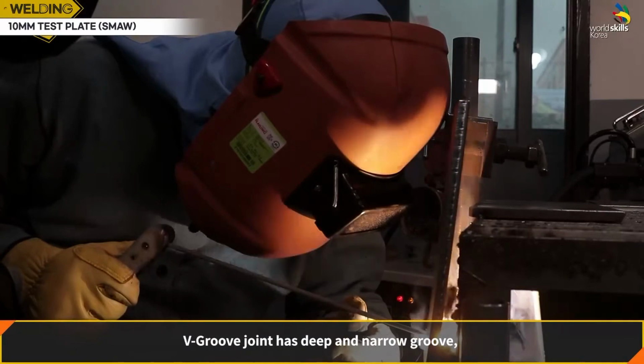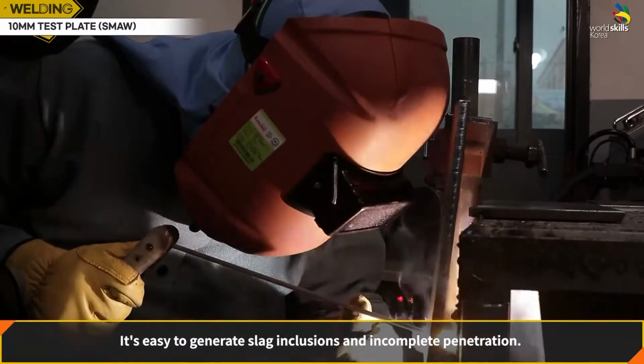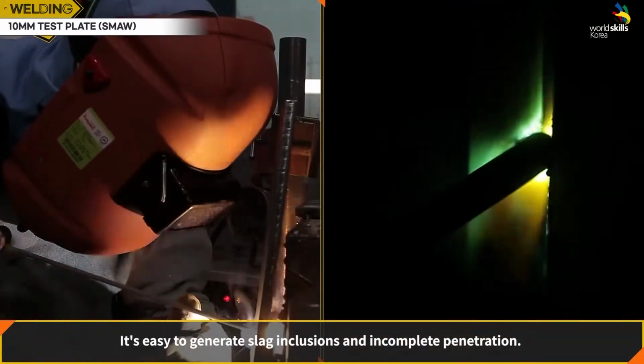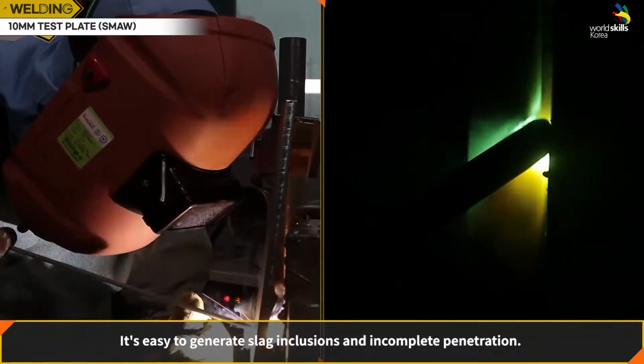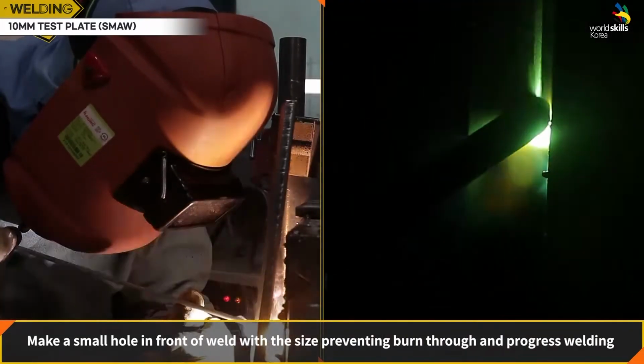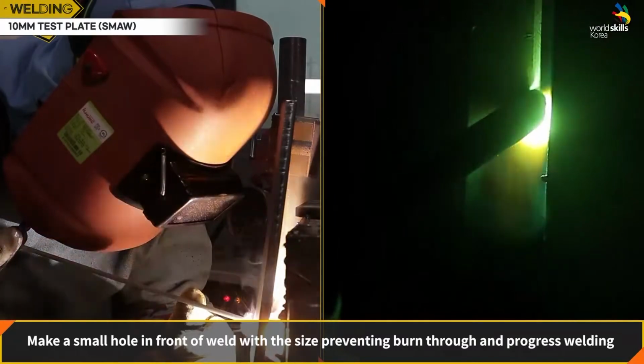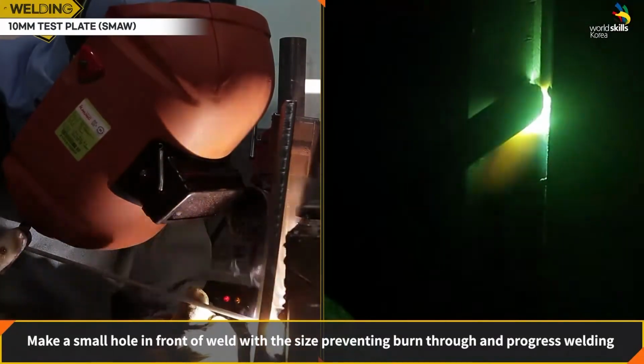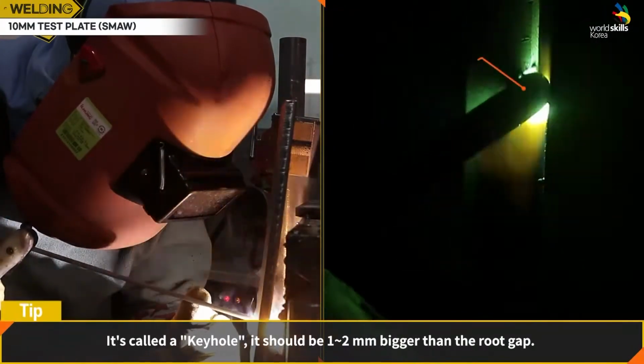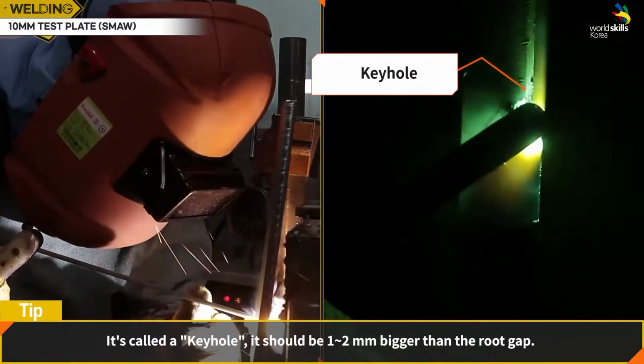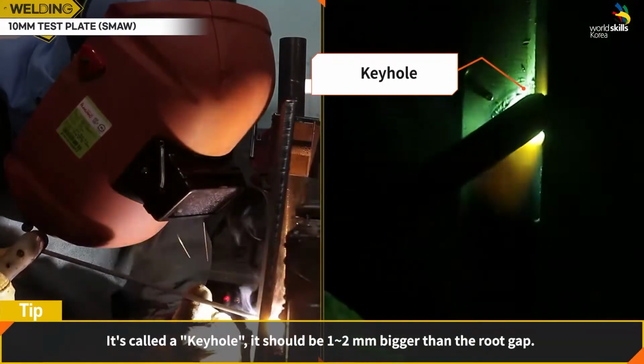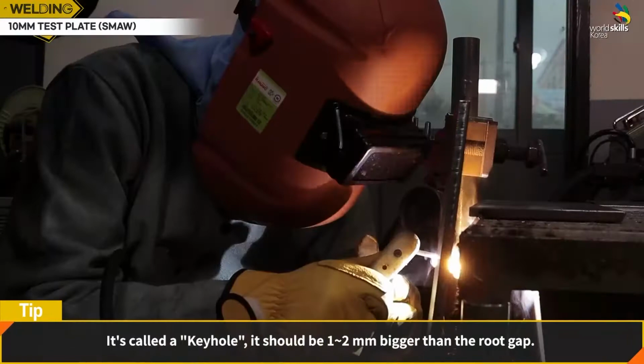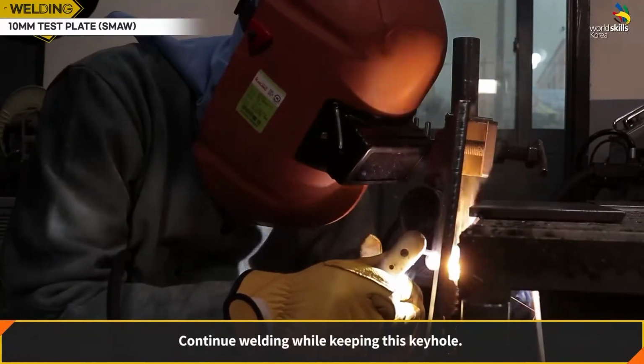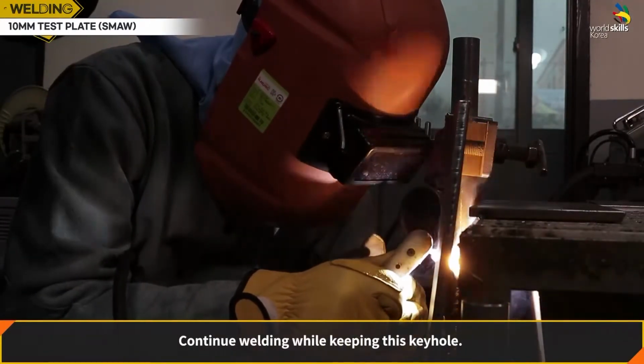V-groove joint has a deep and narrow groove. It's easy to generate slag inclusions and incomplete penetration. Make a small hole in front of the weld, with a size preventing burn through, and progress welding. It's called a keyhole. It should be 1 to 2 millimeters bigger than the root gap. Continue welding while keeping this keyhole.